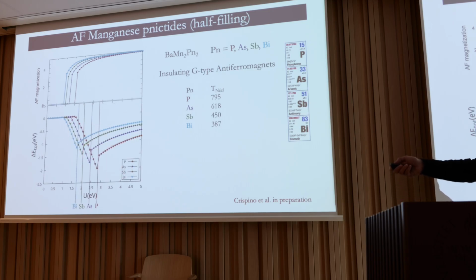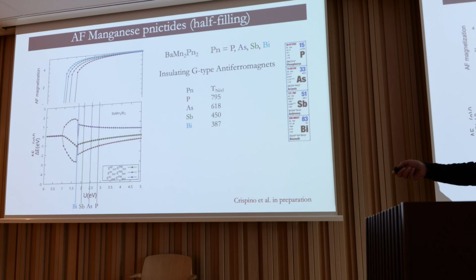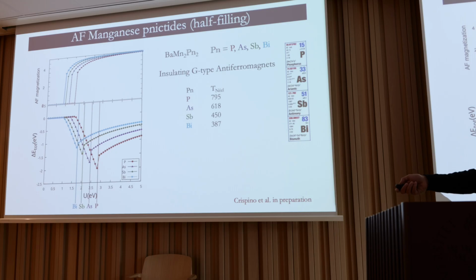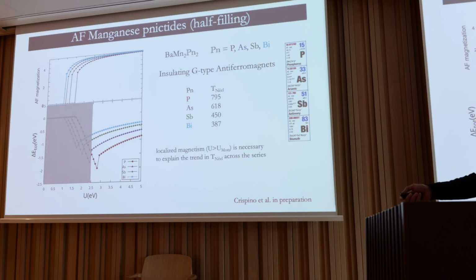All I'm saying is that if we now put the U, the interaction strength with which we model all these systems, and the one that actually was capturing all the correlations of the pnictides realistically, well, you are above this zone. Typically you're here. And in fact, here is where you get the stabilization energy, which can be translated into a Néel temperature.